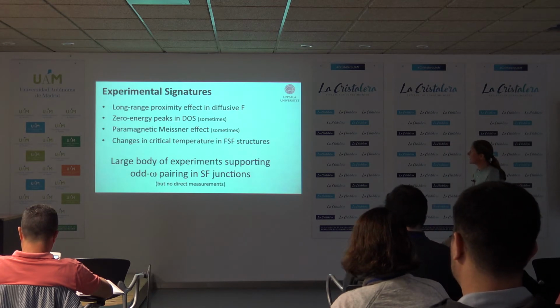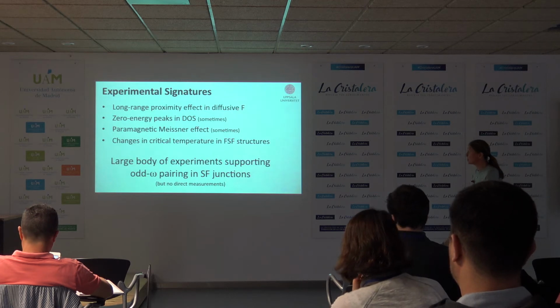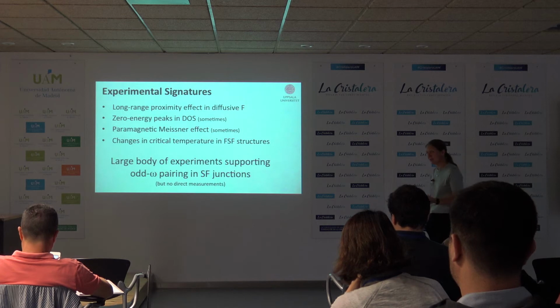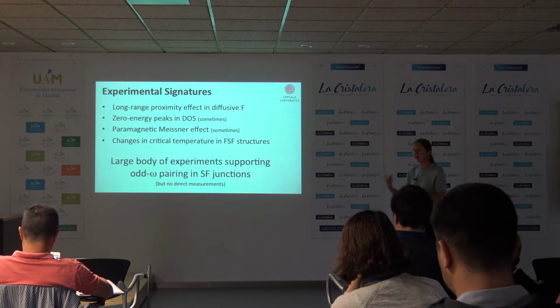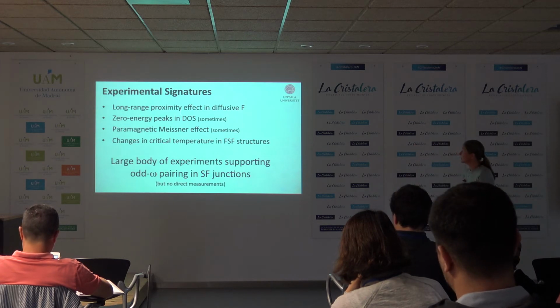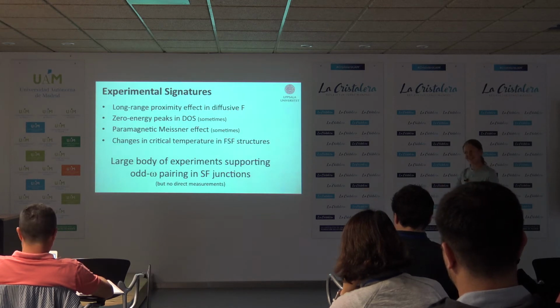This odd frequency state often gives you zero energy peaks in the density of states. This was assumed previously to happen all the time. It actually doesn't happen all the time. There are some criteria on the state, but sometimes this can be a good initial guess at odd frequency in the system.